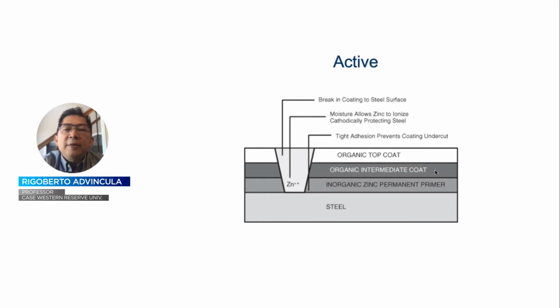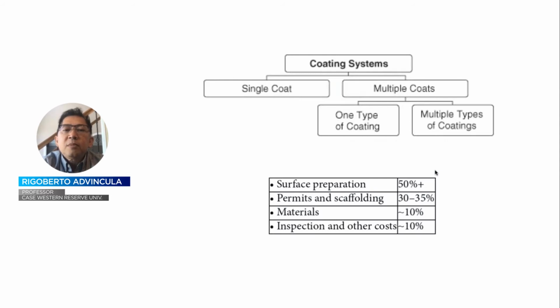An active coating, such as galvanized zinc or other types of self-healing coatings, means that the damage that sometimes occurs on the surface will result in mitigation of that damage by converting, let's say, zinc to zinc oxide, or through other types of anti-corrosion additives that tend to heal the thermomechanical damage on a surface. Okay, so one can say that a coating system is actually, in the majority of cases, a multiple-coat system.